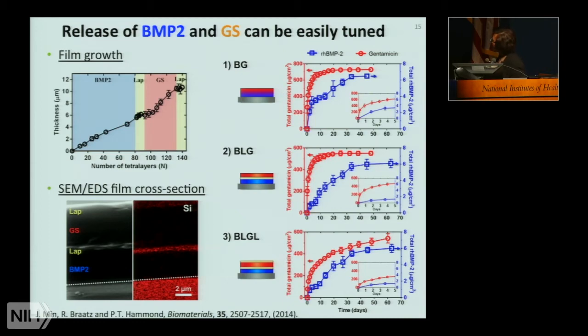If we have this barrier layer in between the 2, it turns out that with the BMP2, we actually can decrease this rate of release. We get, in fact, a 14 times longer release period, or half-life. And you can see this in the blow-up a little bit more easily. You've sort of flattened this curve over the first several days while you're getting rid of infection very rapidly with the gentamicin sulfate. And of course, we can tune this even further with the capping layer.